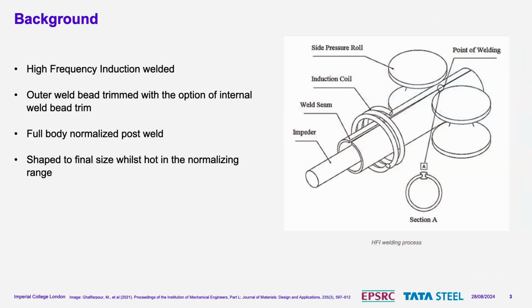So in case you're unaware, these are made by a high-frequency induction welding process. The way we get these is we take a big coil of steel, we fold it over on itself this way, use an induction coil, and the eddy currents in the edges of the steel heat it up very hot, and then you squeeze it together with the rollers. You then get a squeeze-out at the top and bottom, so you get a weld bead, and the default is to remove the external weld bead, and then there is the option of having the internal weld bead removed as well.